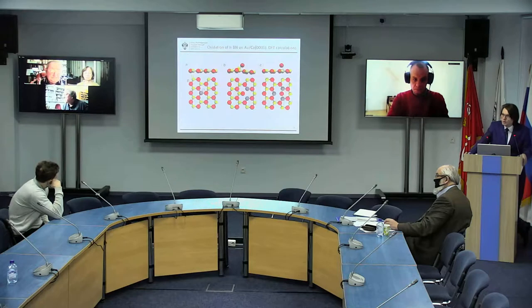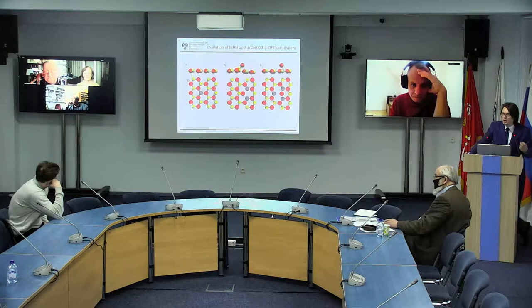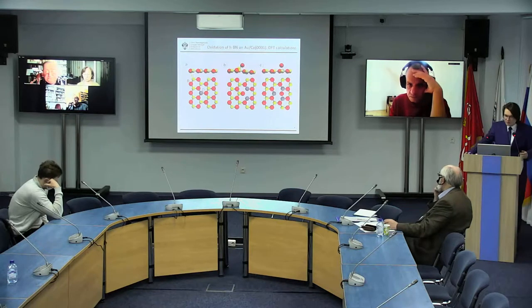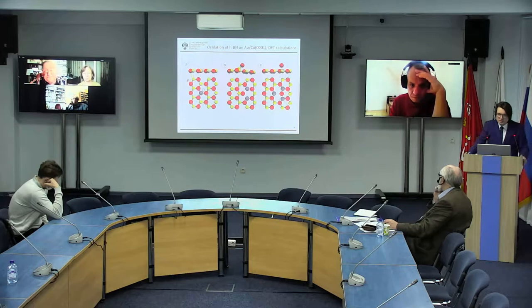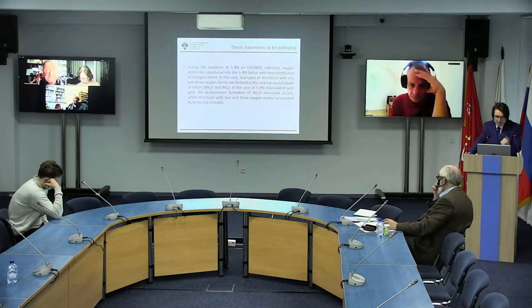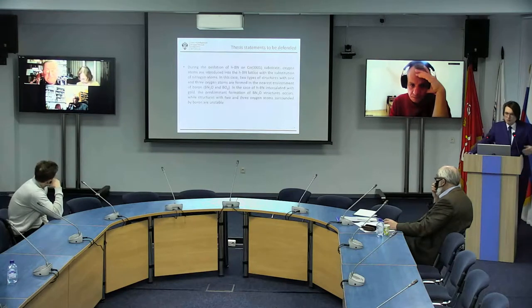In order to explain why the two other types are absent in this case, we carried out DFT calculations that demonstrated that a boron atom bound with two or three atoms of oxygen is shifted from the layer of boron nitride, and this binding energy is characteristic for weak adsorption at increased temperatures. This atom can dissolve from the surface, and this may potentially explain the absence in the spectra of peaks characteristic for these structures.